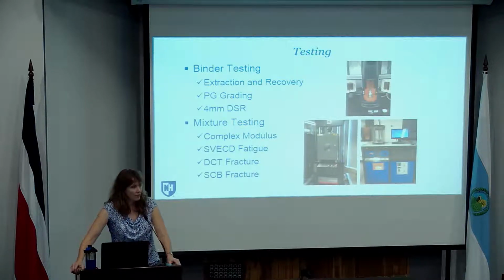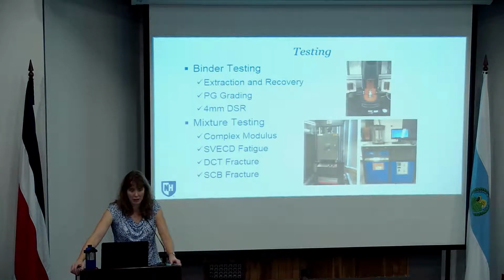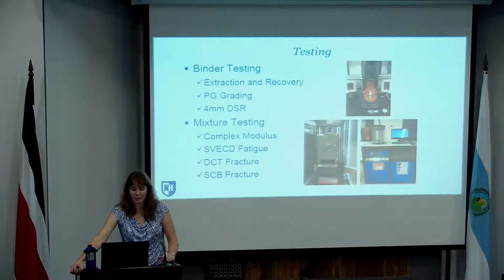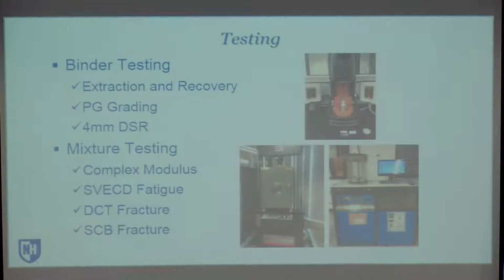For mixture testing, we're looking at complex modulus to establish the viscoelastic or the rheological properties of the material, and then also looking at the simplified viscoelastic continuum damage approach for direct tension cyclic fatigue testing, the disc-shaped compact tension test for looking at low temperature fracture, and the semicircular bend test for looking at intermediate temperature fracture parameters. Okay, and those, again, we're focusing on cracking because that's the primary concern in New Hampshire.